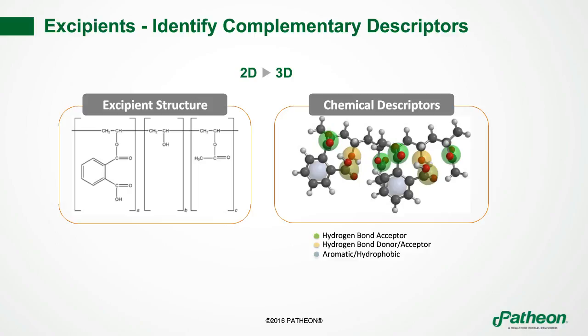These are typically polymeric, and I've shown just a block structure here of PVAP, polyvinyl acetate phthalate. And you can see on the right-hand side of the screen, we've got the same set of hydrogen bond donating, hydrogen bond accepting, aromatic, and hydrophobic descriptor type groups. So the idea is to match the drug with an appropriate excipient based on complementary surfaces and descriptors. Now, as you can imagine, these different descriptors, and the amount of them, change upon drug loading, and other additives that might be included in the formulation.